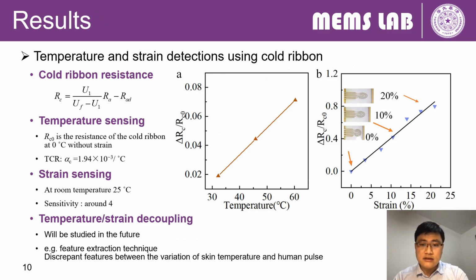Experiments are conducted to validate the sensor's effect of multi-sensations. The left graph here shows the results of temperature sensing using the cold ribbon of the sensor, where the TCR is estimated to be about 0.2% per degree. The right graph shows the strain sensing results using the cold ribbon. The resistance of the cold ribbon increases almost linearly with the applied strain, whose sensitivity is around 4.